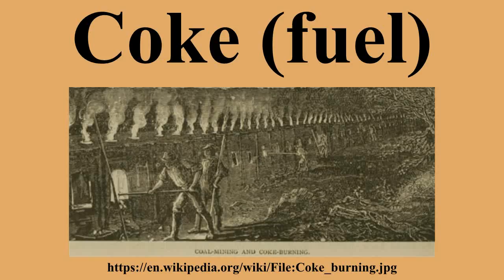Finely crushed coke pieces must not be allowed into the blast furnaces because they would impede the flow of gas through the charge of iron and coke. A related characteristic is the coke strength after reaction index. It represents coke's ability to withstand the violent conditions inside the blast furnace before turning into fine particles.